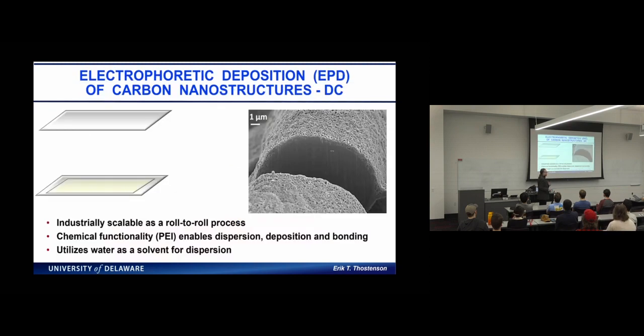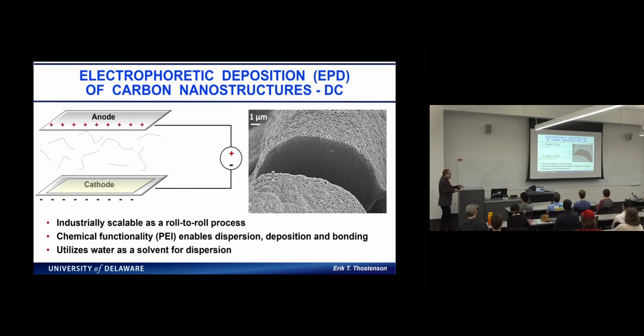So what we started doing was looking at a process that is at ambient temperatures, called electrophoretic deposition. It's something that we can industrially scale. We can study it in the lab and study the chemistry. We can control the chemistry. So what we do is we take the nanostructures. We use mostly carbon nanotubes, but we can disperse a lot of different particles like graphene, and we disperse them in water. And then we have chemically functionalized them.